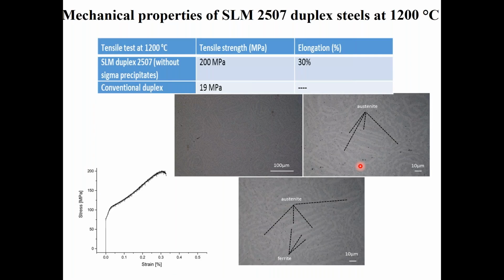Then the mechanical properties of SLM duplex stainless steel at 1200. At room temperature, we got good strength. After heat treatment, we got sigma precipitates that led to poor elongation. But in this case, when we had heat treated without sigma precipitates, we were able to get 200 megapascal with 30% elongation, and we didn't have sigma precipitates.